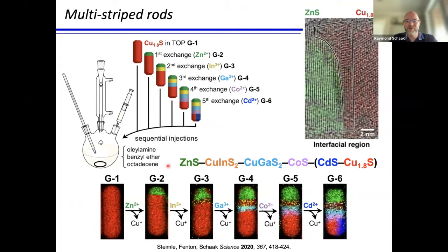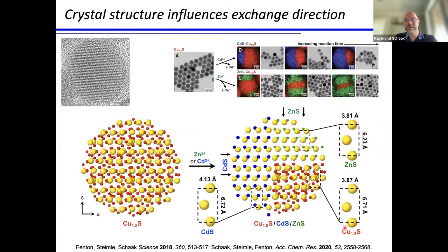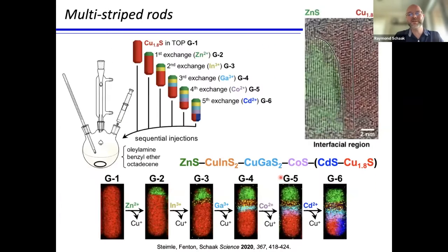And the interfaces between the most recently exchanged part and the remaining copper sulfide tend to be a little bit more disordered, and we hypothesize a bit more reactive, and that tends to be where the next exchange goes. So we're able to step down, in this case, from a tip of zinc sulfide, and put in copper indium sulfide, then copper gallium sulfide, then cobalt sulfide, and then cadmium sulfide, where the interfaces being horizontal or vertical come back to these crystal structure relationships. So there are really some simple design guidelines that enable the made-to-order part.